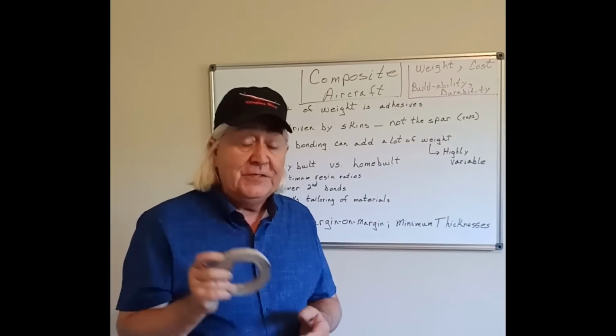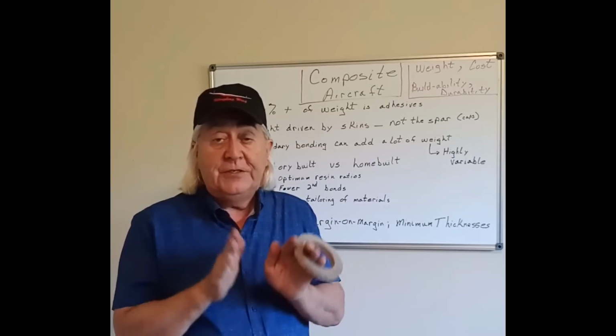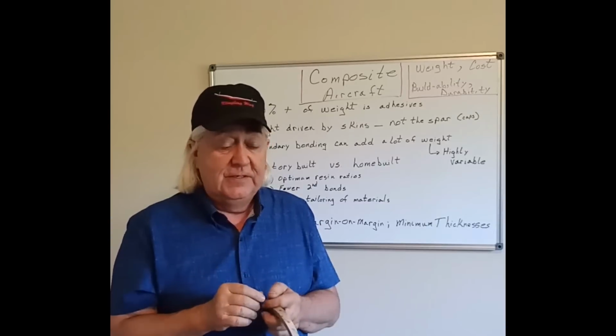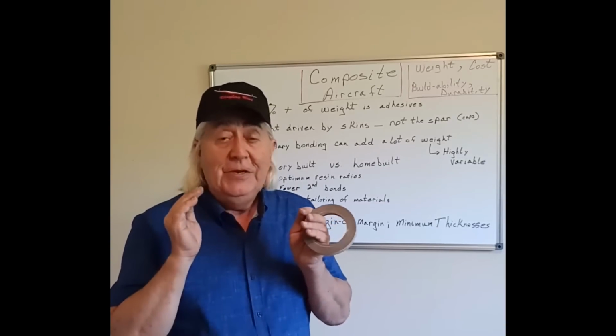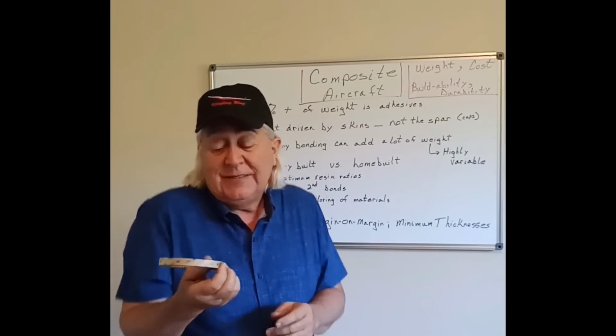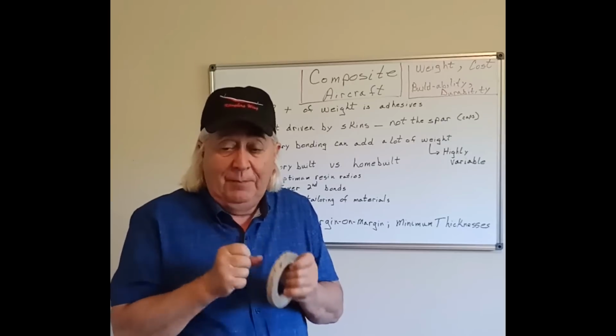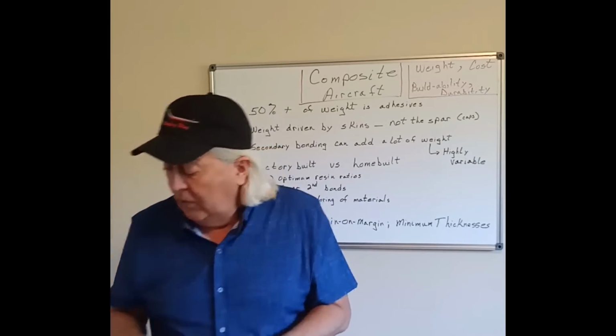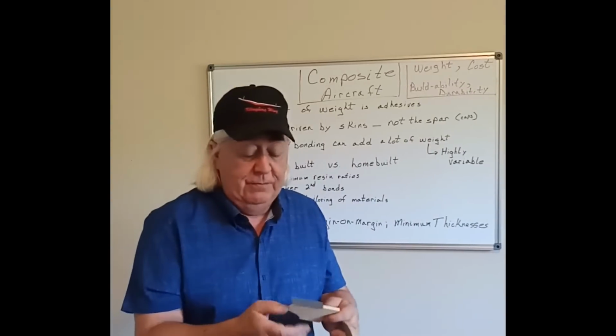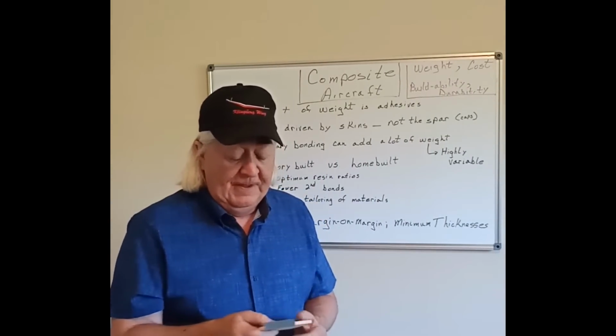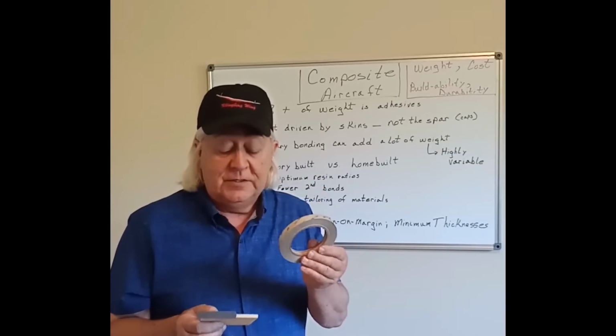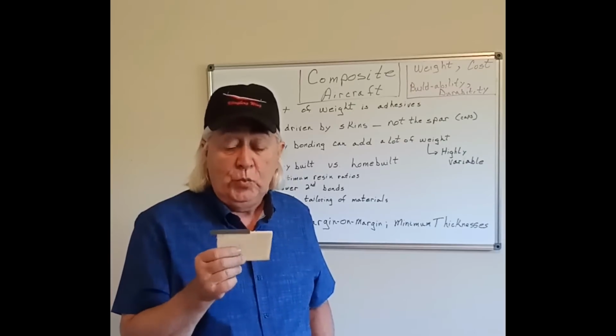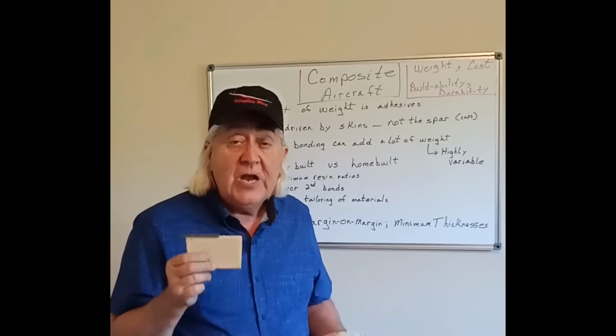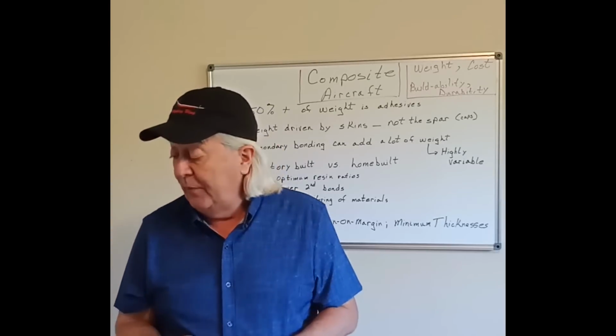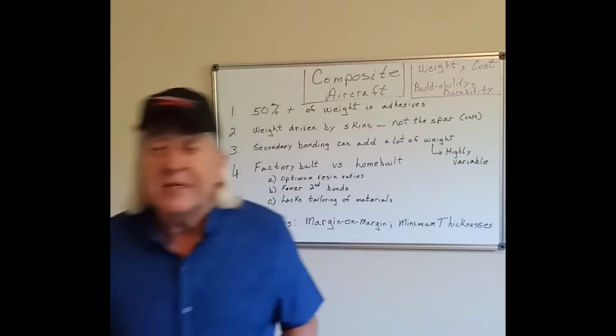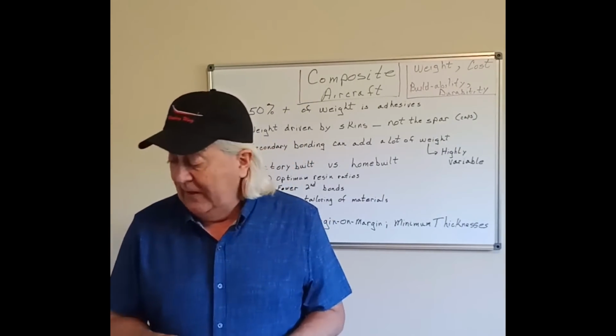So I went to experiment with it. Now, I've used this in the past to put smoothly finished composite parts together, like graphite panels. And wow, it works great. They are just permanently bonded together, especially after about a week. It takes about a week to set up on this stuff. I say set up, but the bond gets better over time. So I tried using this on the urethane foam with the carbon fiber cap strip. And I could not get this stuff to bond well to either surface because these surfaces aren't really smooth. And there's just not enough bond area. So that pretty much killed the tape idea. And I heaved a sigh of relief because it's so darn expensive. So there we are.